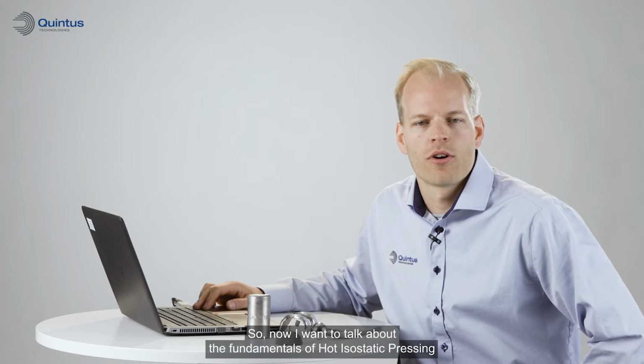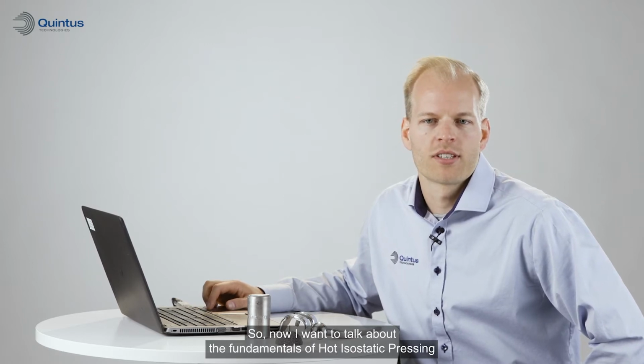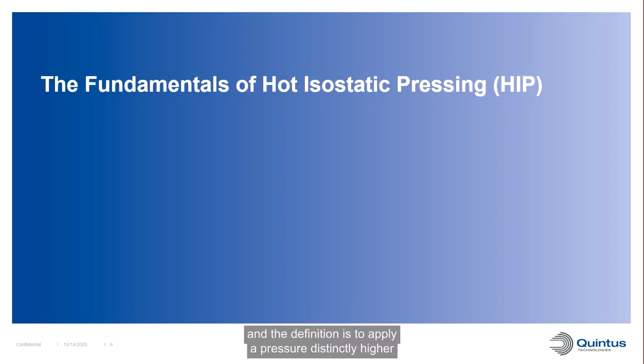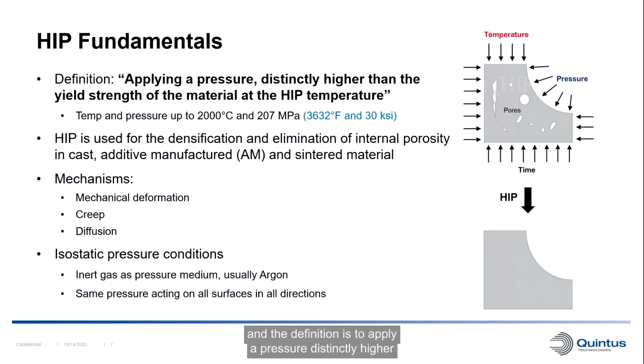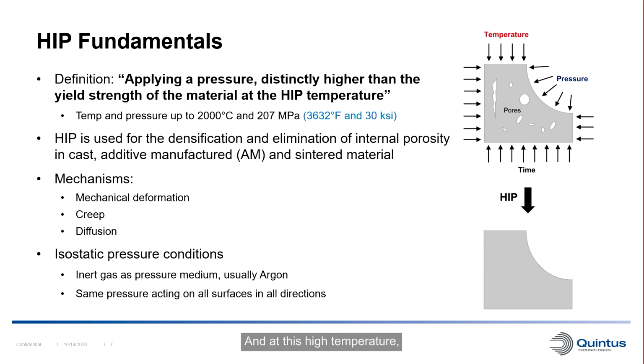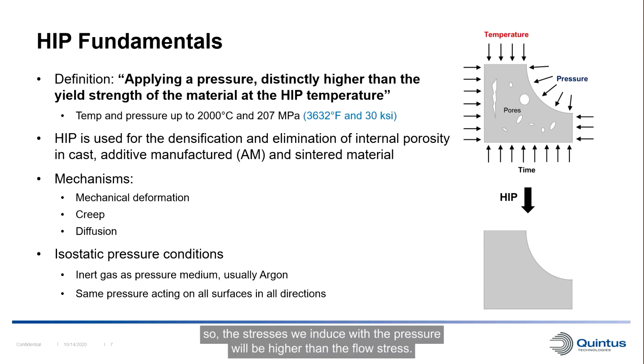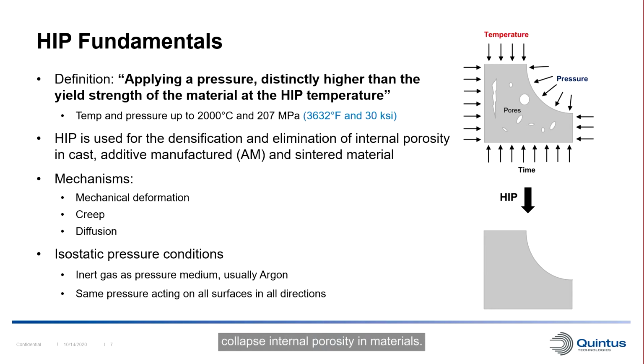So now I want to talk about the fundamentals of hot isostatic pressing. The definition is to apply a pressure distinctly higher than the yield strength of the material at the HIP temperature. So it is a process with high temperature and high pressure. And at this high temperature, the flow stress of the material will be very low, so the stresses we induce with the pressure will be higher than the flow stress. So the material will plastically deform to, for example, collapse internal porosity in materials.